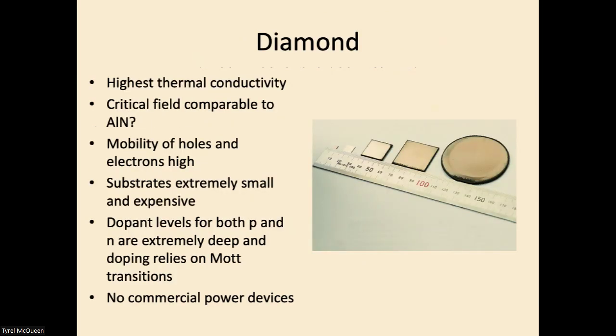So diamond, if you want to talk figures of merit, diamond blows everything out of the water in terms of figures of merit. And that is due to this extremely high thermal conductivity and the predicted critical field. The mobilities of electrons and holes of diamond are very high. However, the substrates are extremely small and expensive, and the dopant levels are extremely deep.